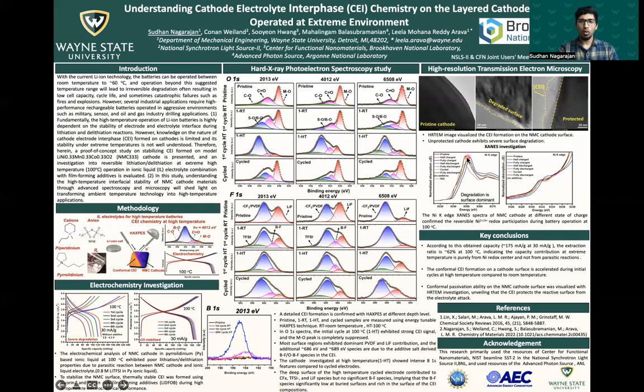And we wanted to confirm that the degradation phenomenon is majorly from the surface region. So we investigated transmission mode bulk sensitive XAS spectra, and here we have confirmed that nickel is the redox couple in NMC cathodes. That was confirmed using XAS spectra at different states of charge.